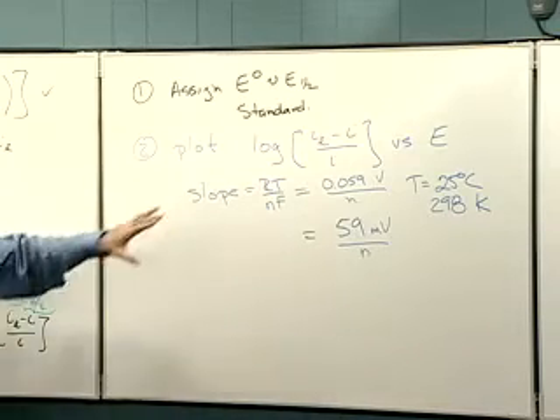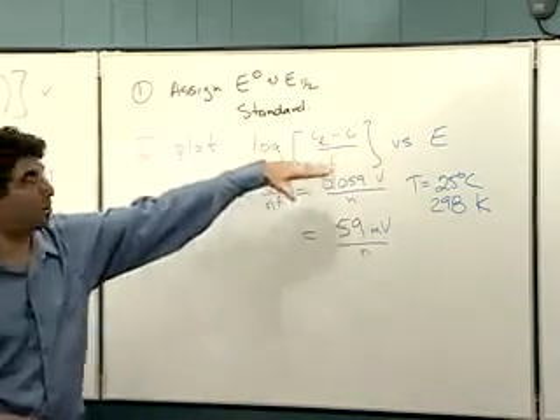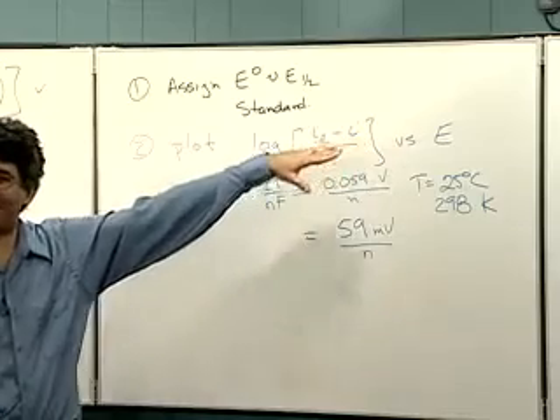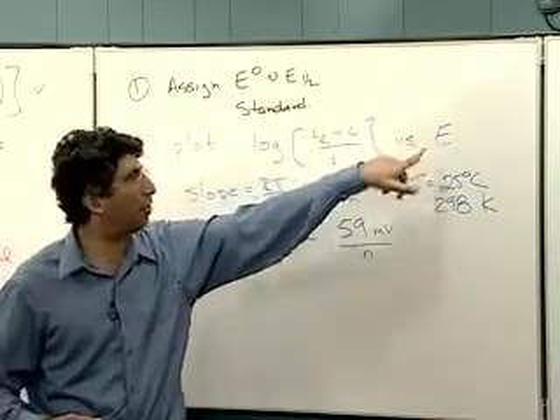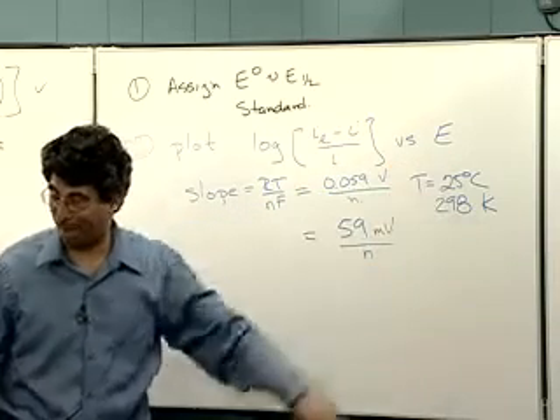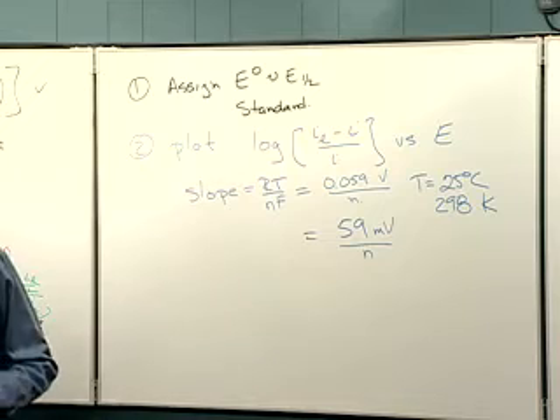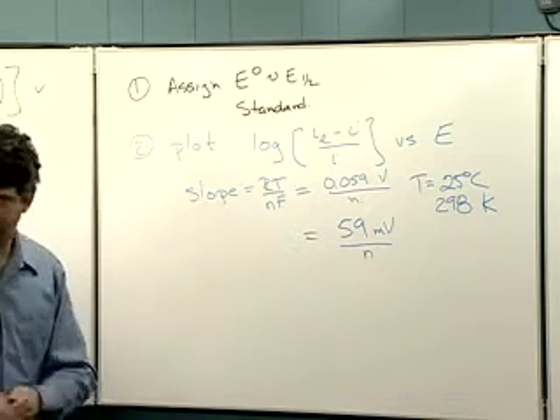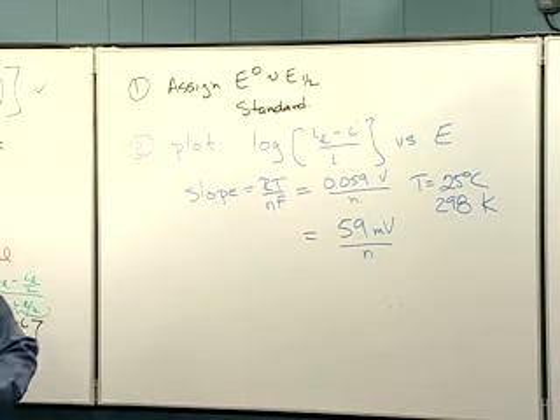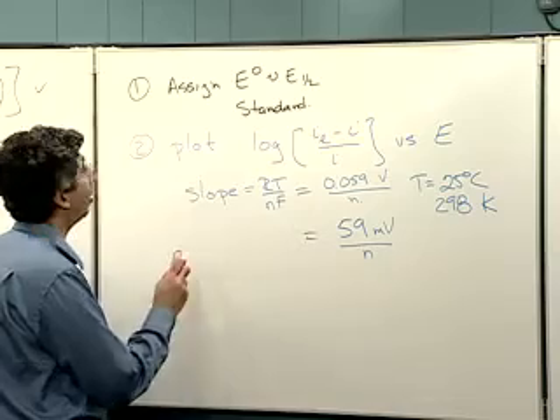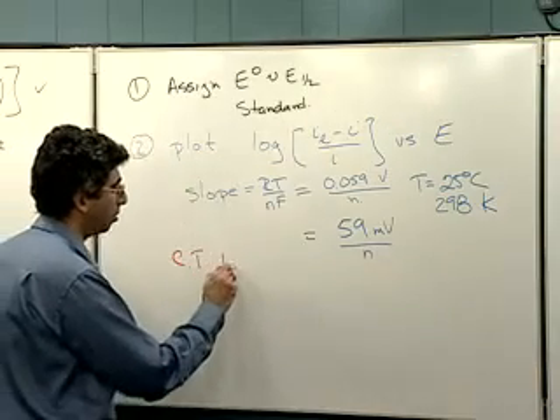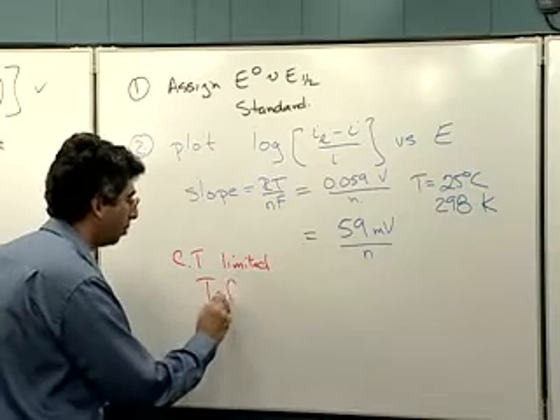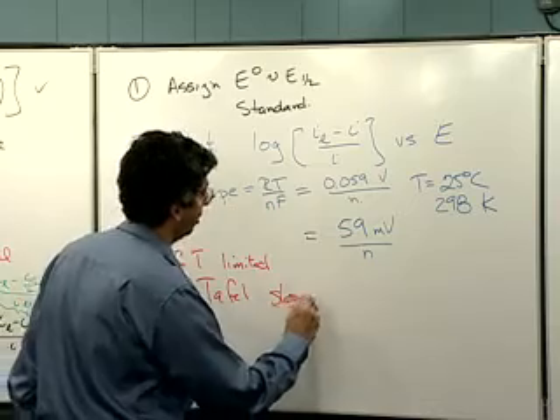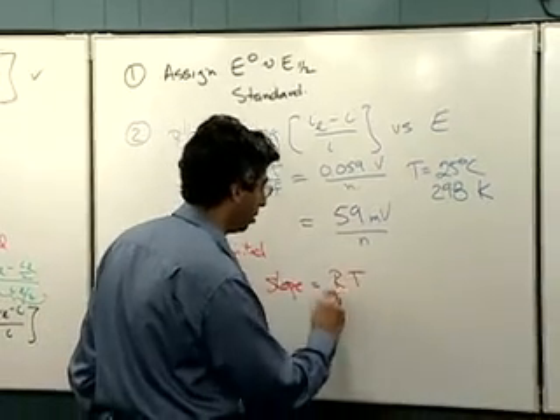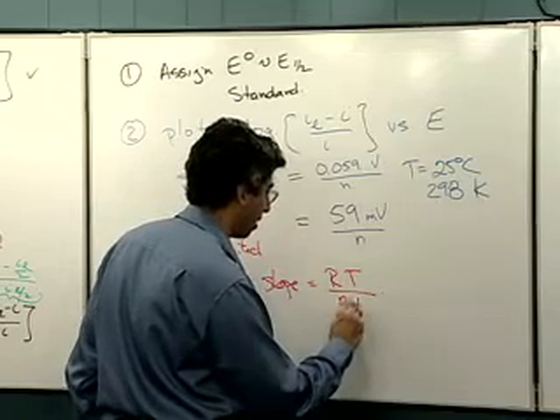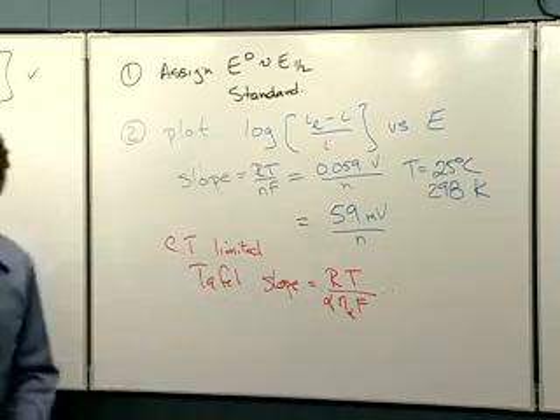What will actually happen, if you look at that plot that I'm suggesting you make there, is something very similar to the Tafel plot, right? And the Tafel plot is log of current versus the overpotential. And the overpotential and this number scale with each other, right? So in the Tafel equation, I'm going to expect a similar straight line dependence if, instead of being mass transfer limited, I am charge transfer limited, then Tafel will have a slope that's equal to RT over, here's my ambiguous nF, I'm going to put a little alpha down there, and I have to throw another alpha in. So it'll have a different slope.